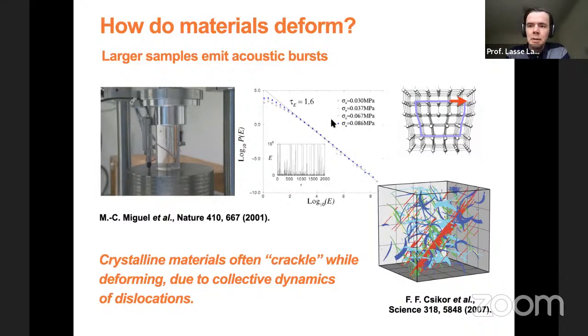So you have this critical-like signature of the plastic deformation process, also in these large crystals where you don't really see anything interesting in the stress strain curves because these are smooth, but yet you still observe this crackling noise, if you like, coming from the crystal, even in this case. So the general conclusion is that the crystalline materials, when they deform, they crackle. So in the small systems, they display this strain burst, which can have a broad distribution. And in the larger system, there are acoustic emission events.